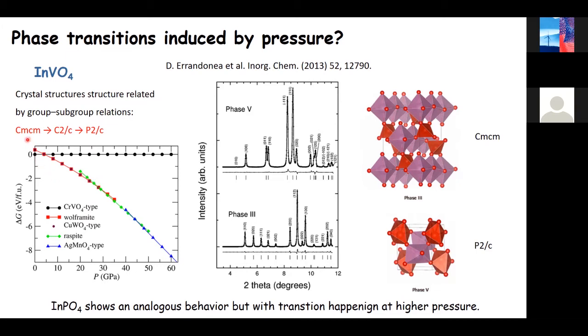Another interesting thing is that we can go from the low pressure phase to the high pressure phase just by using group-subgroup relationships. We can transform this orthorhombic structure into a C2/c structure, which can be easily transformed into the P2/c structure. So these group-subgroup relations give an idea of the possible mechanisms driving the phase transition.